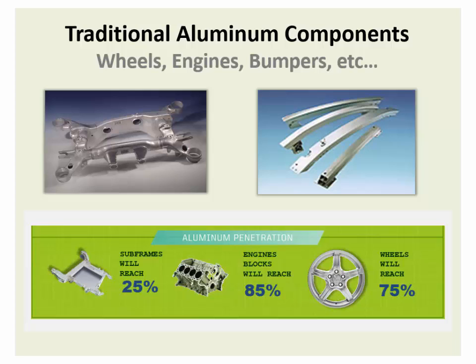That'll be the end of our comments on sheet, and just so we don't lose track of the fact that the casting and extrusion businesses in aluminum are alive and well, and also part of the support necessary to meet industry growth between now and 2025 and beyond. We have a lot of extruded product. Subframes will reach 25% share of the market by 2025. Aluminum blocks will remain around 85%, we feel, and wheels up to about 75% of the market from about 65% now. Wheels have been between 65 and 75% of the aluminum market for the last 25 years. That's about the balance point for the demand on aluminum wheels.